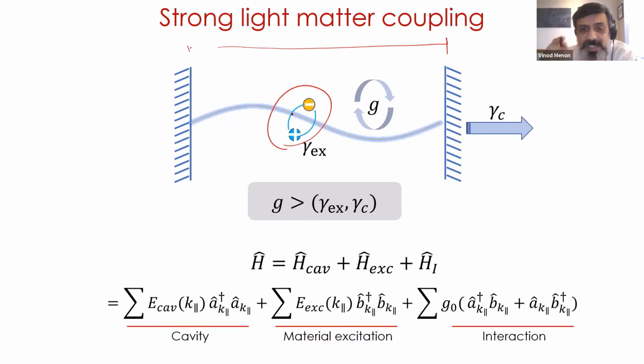And what you will see is that if the interaction between the material excitation and the cavity photon, given by the small g, is greater than the damping rates of both the material excitation and the cavity photon. So you remember, the cavity photon can leak out, and the exciton from its excited state can come down. So both of these are the individual damping rates. If these individual damping rates are less than the interaction rate between the two systems, then you enter into the strong coupling regime.